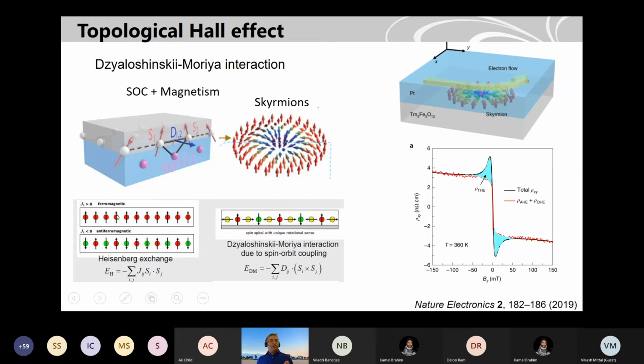In a ferromagnet or antiferromagnet, you know how the interaction takes place between two spins, interacting with the exchange constant. But when you have spin orbit coupling added to this magnetism, you will have an exchange interaction which is called DMI, the Dzyaloshinskii-Moriya interaction. This interaction can produce spins in a canted structure, and you will find magnetic structures, for example, called skyrmions. They can be very small, from a few nanometers to even hundreds of nanometers, and that can be controlled with different materials and interfaces, or spin orbit coupling and magnetism.